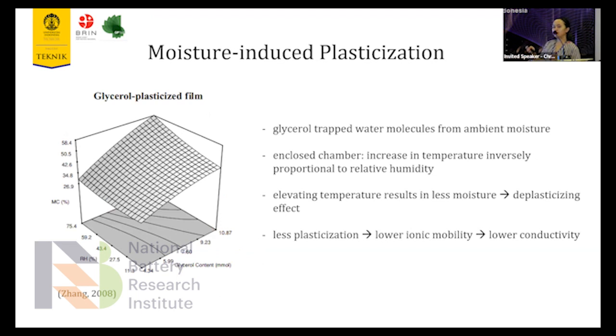So what is causing this? It is the moisture-induced plasticization. We know that glycerol is very hygroscopic, and glycerol traps water molecules from ambient moisture. In an enclosed chamber, the increase in temperature is inversely proportional to relative humidity. So elevating the temperature, or heating, results in less moisture. So there is a deplasticizing effect, and less plasticizing means lower ionic mobility and lower ionic conductivity.